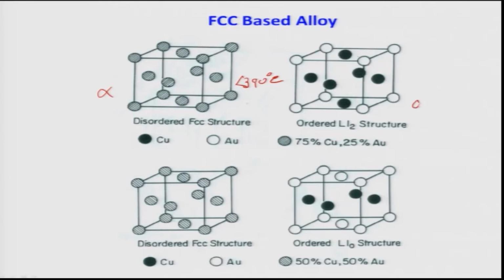That is why you actually get Cu3Au compositions, and this structure is known as the L12 structure, because this structure is not the same as an FCC structure. So, we have to have a different notation to demarcate that. So, that is actually a disorder to order structure. The disorder structure was this, and the order structure was the right hand side.